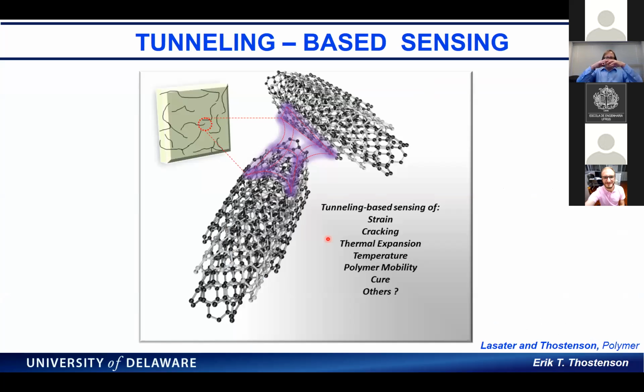It's really this electrical tunneling, the contact resistance between the individual conductors that's added up over the network. In this case, it's just tunneling based sensing. So it's strain and cracking that we're looking at. We've also done work with thermal expansion, measurement of polymer mobility. We published a paper where we could measure both curing as well as glass transition in situ. And it also has some thermal resistive aspects that we can take advantage of.